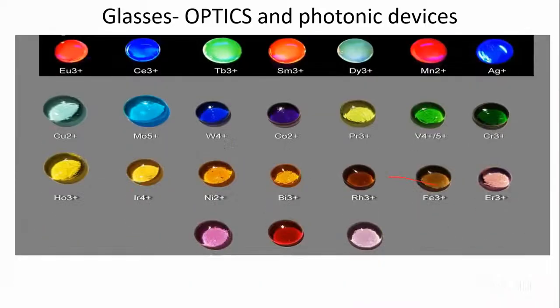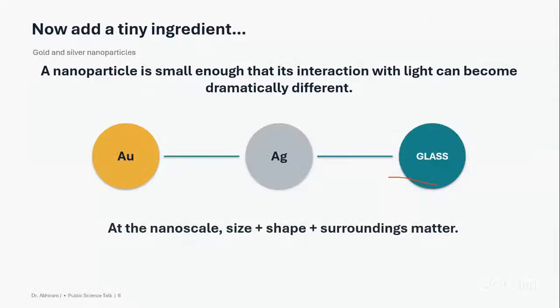So now, with respect to the colors, you can see this particular europium, cerium, samarium, dysprosium, manganese, silver, they are all showing these particular shades in this blackish region because it is with respect to the exposure of UV light. Whereas these colors that are being obtained for the other transition metal elements, it is because of the visible region.